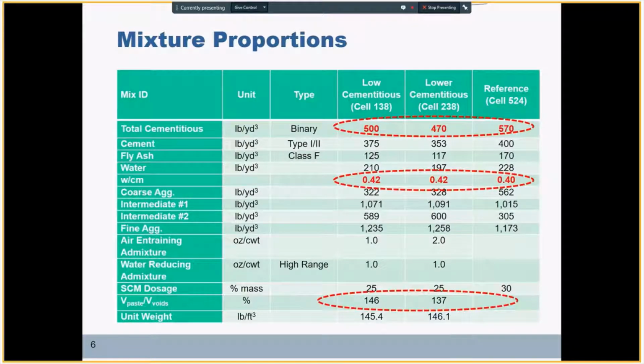Here I have a summary of the mixture proportions. As you can see, section with low cementitious material, we have 500; with lower cementitious material, we are at 470 pounds per cubic yard of cementitious material. Both concrete mixtures are proportioned with a 0.42 water cementitious materials ratio, and in both of these mixtures we have 25% replacement of class F fly ash.